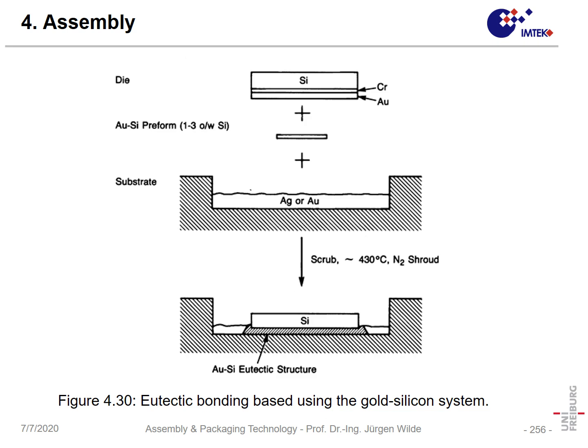Unfortunately, silicon has an oxide layer, so typically we have silicon oxide, and that would prevent wetting with gold, and so the silicon oxide would keep the gold and the silicon apart, and so there could be no eutectic reaction because there is just a layer in between. For that reason, the silicon chip is typically coated with a chromium layer and a gold layer, and the silicon oxide must have been etched away before the chromium is put on.